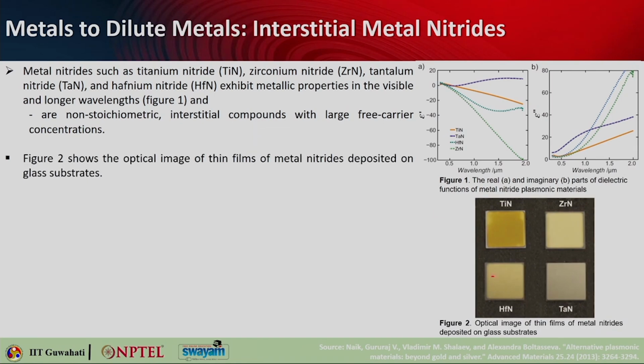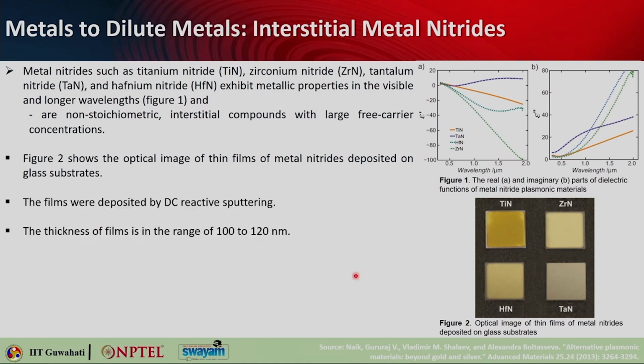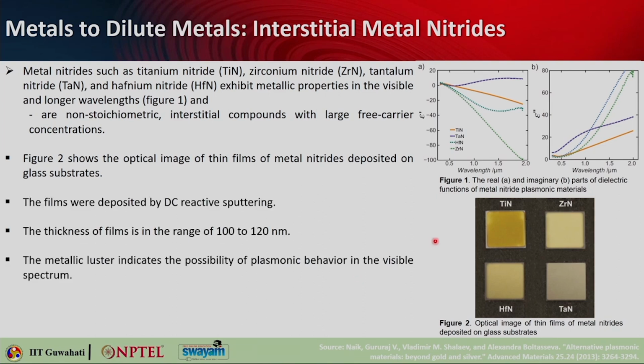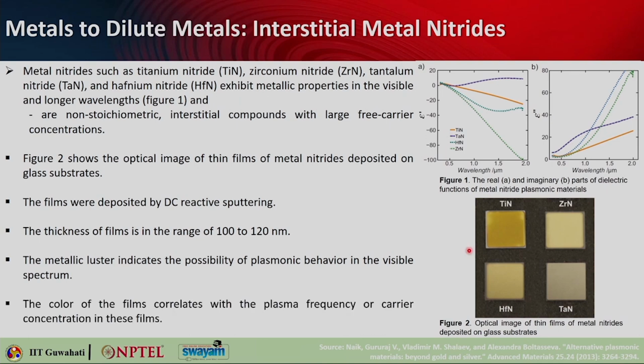Here you can see the different optical images of the thin films of metal nitrides which are deposited on glass substrate, and these films are basically deposited by DC reactive sputtering. The thickness of the films is in the range of 100 to 120 nanometer, and you can see metallic luster, okay, from the films, and that is showing the possibility of the plasmonic behavior from these films in the visible spectrum. The color of the films correlate with the plasma frequency or the carrier concentration in these films.